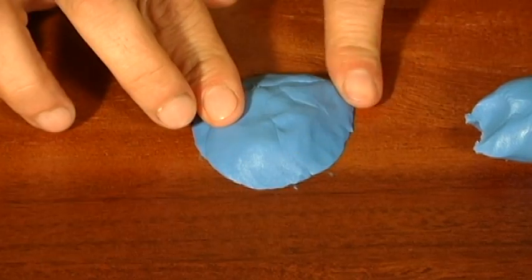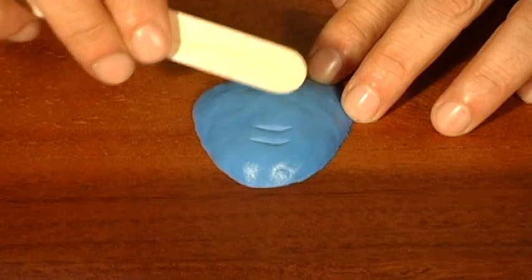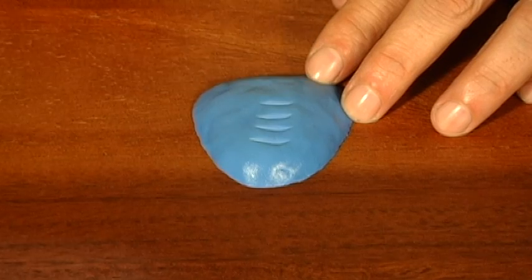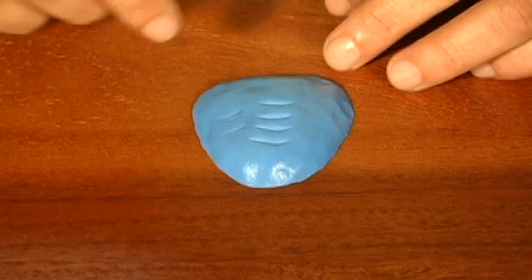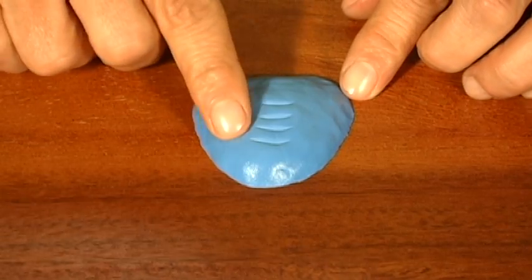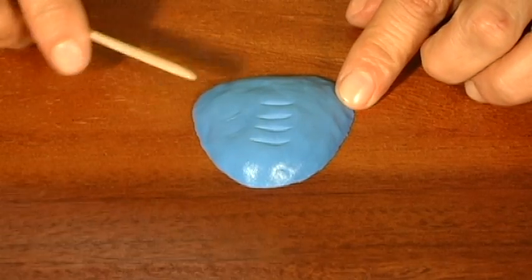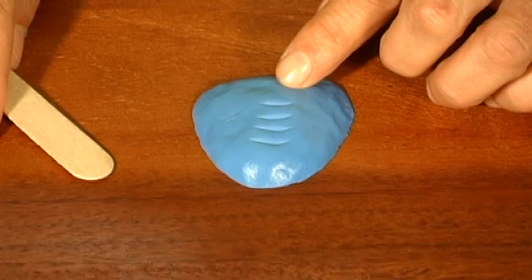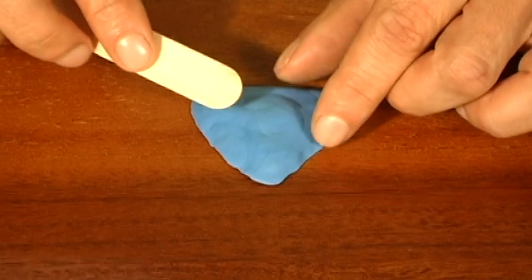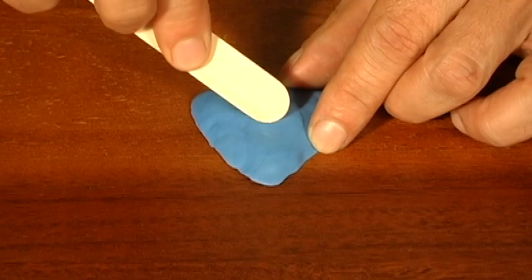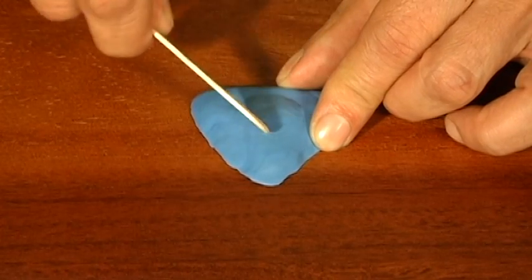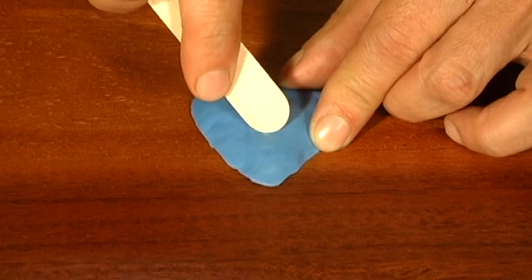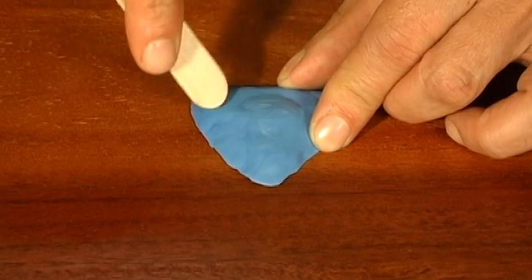To determine when silicone plastique is cured, simply press with the edge of a coin or tool to see if an impression stays in the surface. If it does, that means that more time is required for a complete cure. If the silicone springs back and no mark is left, this is a good indication that the silicone plastique has completely cured and can be removed from the object.